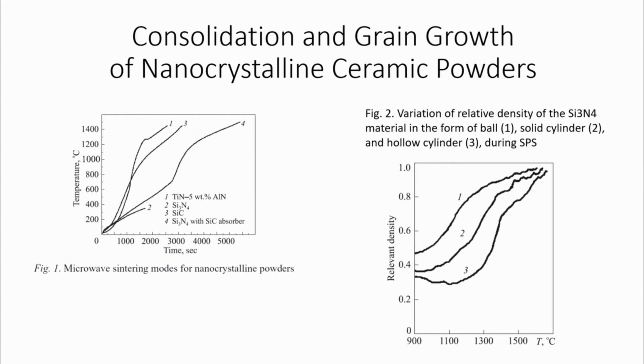To fully utilize the unique properties of bulk nanocrystalline materials, nanometer size powders must undergo densification to form parts with specific properties, geometry, and size. The critical aspect of nanopowder consolidation is achieving a high densification rate while minimizing microstructural coarsening and preventing undesirable microstructural transformations such as grain growth during sintering's intermediate and final stages, the Ostwald ripening process. While the densification process for conventional powder is well understood, densifying nanopowders presents significant additional challenges from both theoretical and practical standpoints.